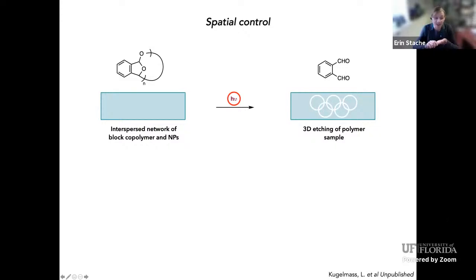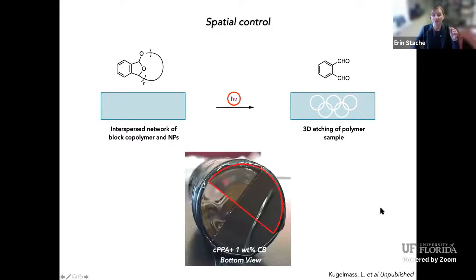Now, the advantage of using photothermal heating versus bulk heating is that you should be able to get spatial control. You should have all the spatial control of visible light and the temporal control of visible light. And so we question whether or not we could take a film of the polymer and the nanoparticles and expose just part of it to light. Would we be able to see the spatial resolution and only see depolymerization where we're shining the light? And so we made a very crude photomask just to start. This is just electrical tape over a scintillation vial, and this semicircle represents the film, 1 weight % carbon black.